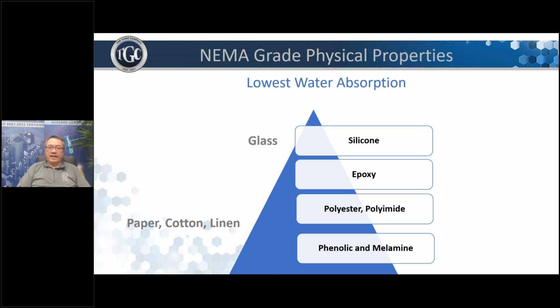Essentially, what prolonged exposure to high humidity would do is that it actually degrades both the resin and the fiber through a chemical reaction called hydrolysis. And also the water film will form a boundary, and that will cause partial discharge at certain voltage that's high enough, and that would affect the long-term performance or the longevity of the insulation used. So that's why water absorption is a very important physical property.